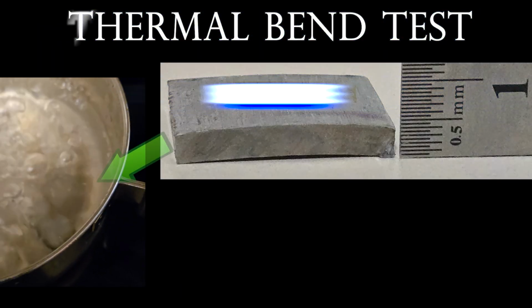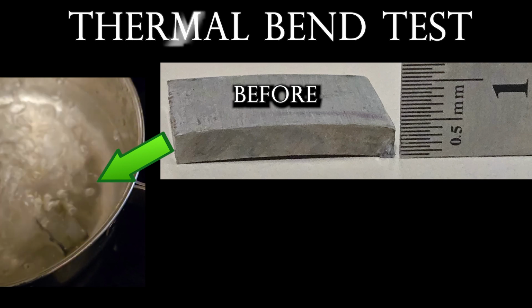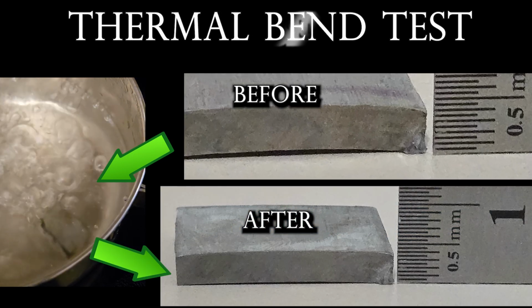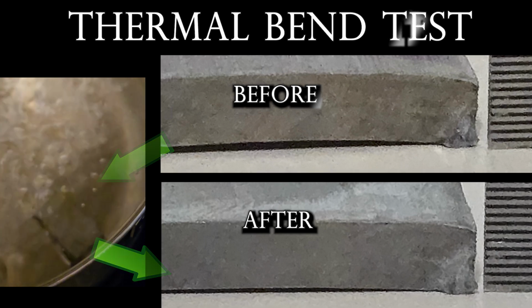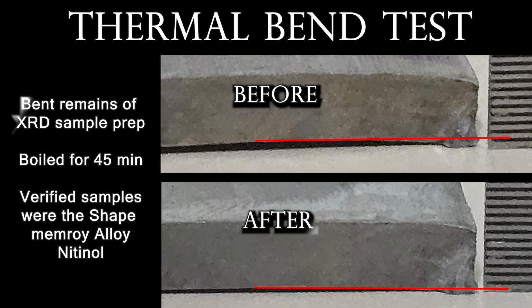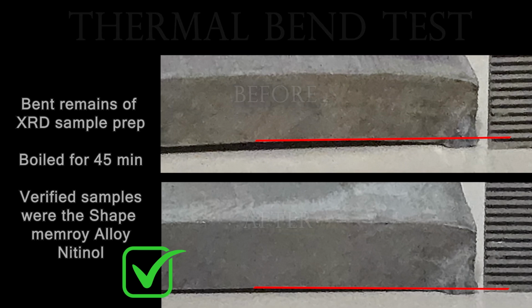To quickly verify that our sample was indeed nitinol, we plastically deformed it with a noticeable bend and then placed it in boiling water. The sample returned to its original shape, confirming the shape memory effect characteristic of nitinol.